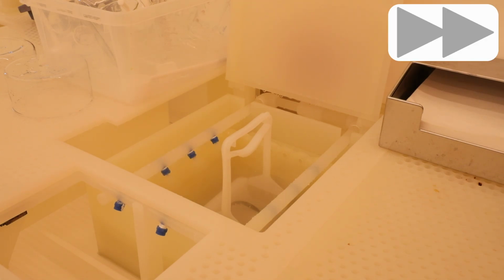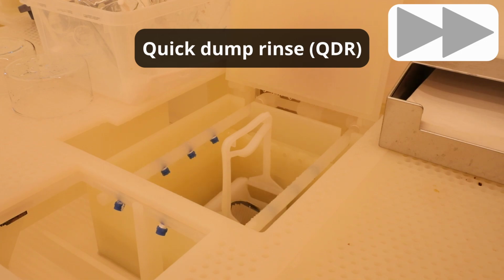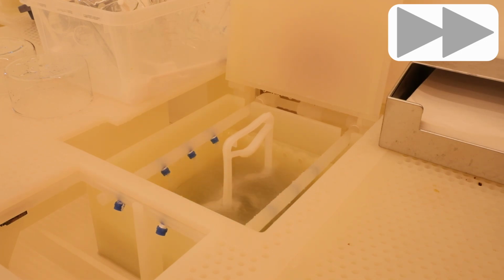The wafer is currently taking a swim in what we call the quick dump rinse bath, which goes through several cycles of spraying the wafer and filling the bath with pure deionized water and then dumping the contents. This ensures that the acid is properly rinsed off the wafer surface, which is important not only for the safety of the people handling the wafer, but also so that there are no acid residues that can further corrode the metal after we're done with the etching. Incidentally, I have also used the quick dump rinse after the HF treatment back at the very start of this fabrication process, but there the copious rinsing was mostly there for human safety rather than that of the wafer.